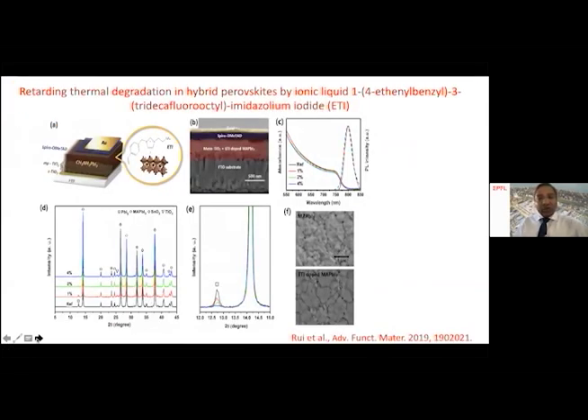Now I show you two examples of composition engineering itself. So the perovskites, you have a lead iodide and either methyl ammonium or different organic halides mixed together. And here we have used ionic liquid. Now the question is why we are using ionic liquid. Perovskite is an ionic compound. When we have these ionic compounds, there is ion migration within the composition. That's one of the reasons why the perovskite is not very stable. Can we increase the stability of the perovskite composition by using this type of ionic liquid, which creates an ionic environment and reduces the ion migration? That's the purpose of this ionic liquid.